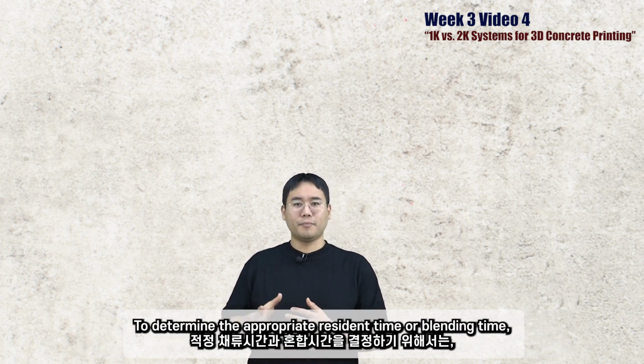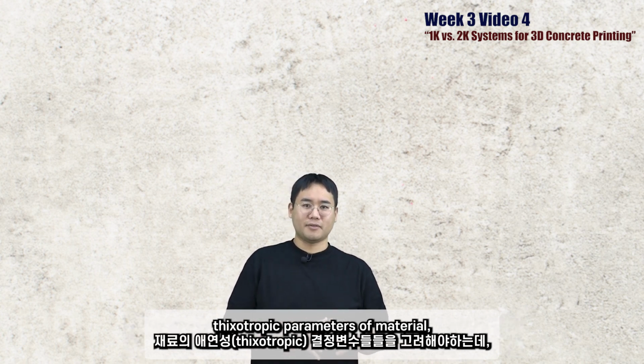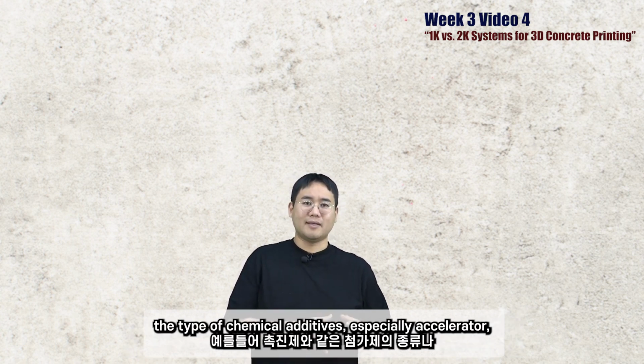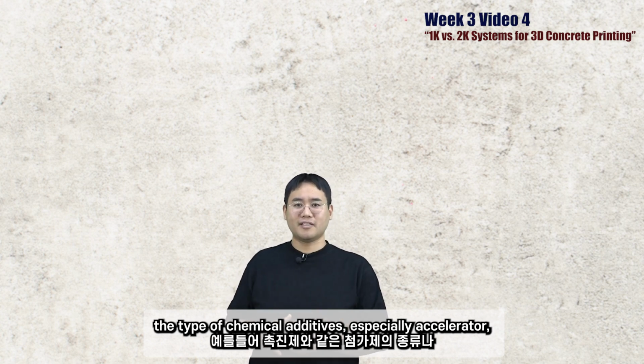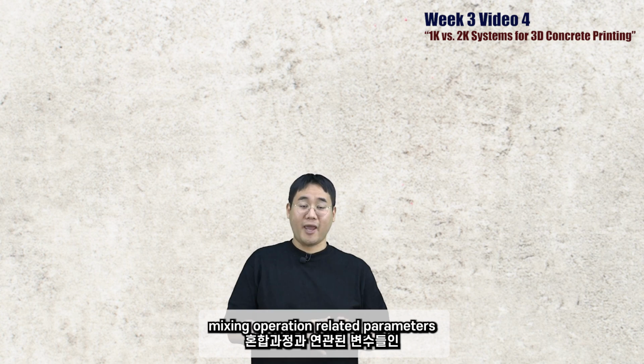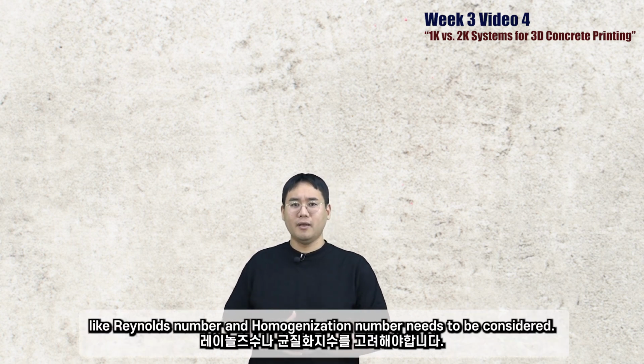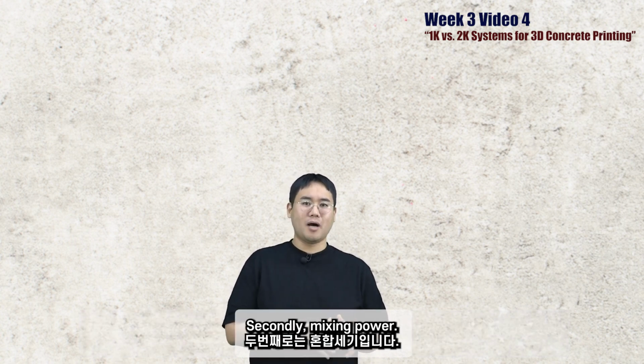To determine the appropriate residence time or blending time, the thixotropic parameters of the material and the type of chemical additives they are using, especially the accelerator, need to be considered. The mixing operation related parameters like Reynolds number and the homogenization number need to be identified or considered for the design.